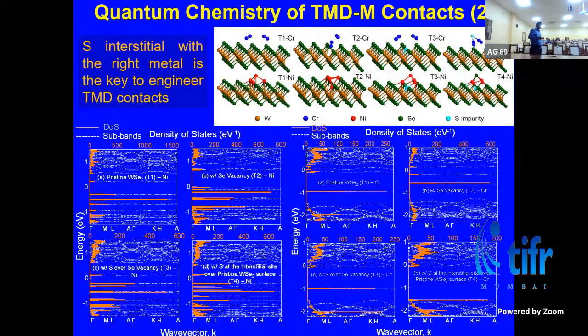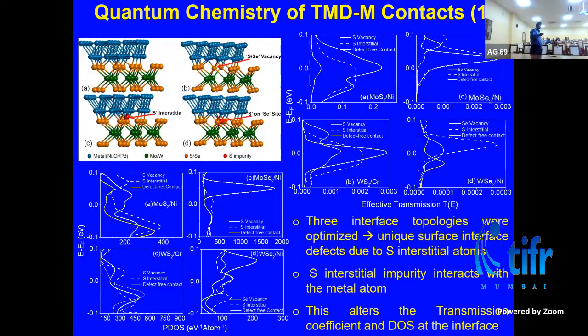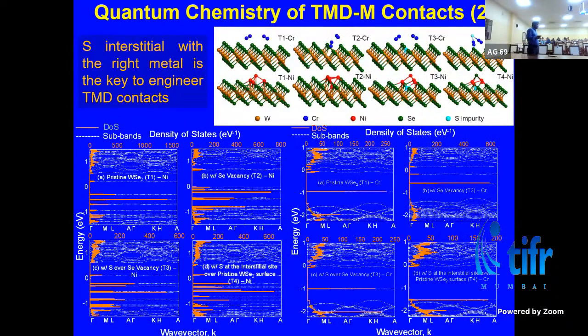Now, I'll skip the details, but what we found is, if you just do the vacancy and the interstitial, nothing happens. What I'm going to show you is the function of the metal being present on top of it. Just having these vacancies and defects doesn't change much in terms of what I'm going to talk about. But when you have this metal on top of it, depending on the metal that you choose, you get either donor states or certain acceptor states, right?